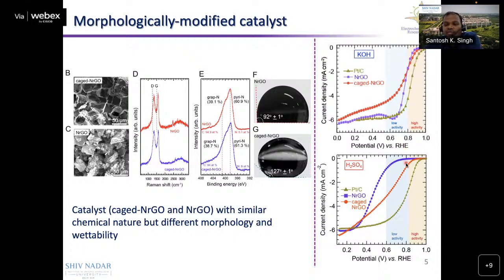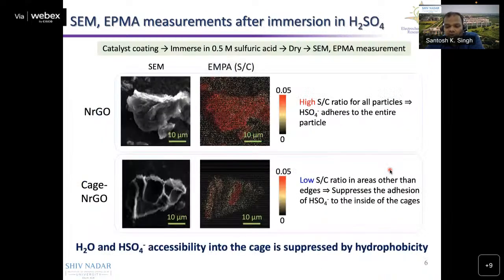However, when we employ them in the acidic medium, we can see that the caged NRGO hydrophobic catalyst shows very close activity to platinum. However, with similar chemical composition, the hydrophilic catalyst shows very low activity. So what is the reason behind it? We had already anticipated that the hydrophobicity is responsible for this. But how the hydrophobicity controls this reaction, we studied by different methods.